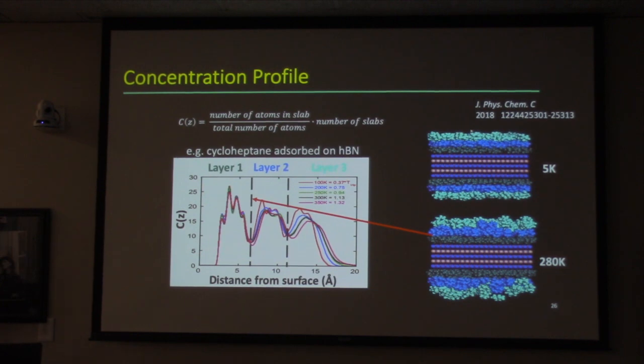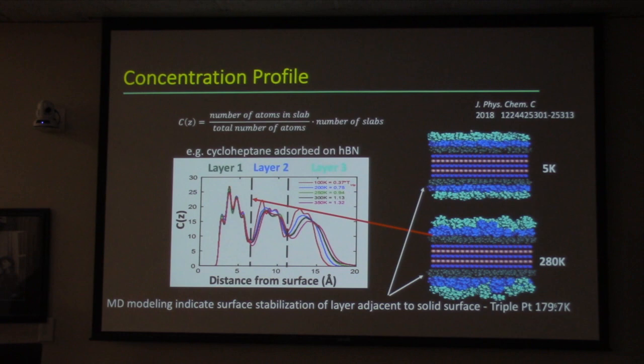And it's mostly because the upper layers act like a piston. They're attracted to the surface enough that they keep the molecules in the interface organized. My dear friend Stuart Clark and Tom Arnold, who did a postdoc with me, measured some differential scanning calorimetry, and they saw a peak where they would see the bulk melting, and then, depending on the particular molecule, another peak that they thought had something to do with the melting of the surface. When I was still at Brookhaven, we did this with argon and saw the same thing. Argon's surface layer melts about 20% above the bulk triple point. That had a lot of interesting science and caused a lot of head scratching and then finally some understanding, which is, again, a satisfying thing for science.